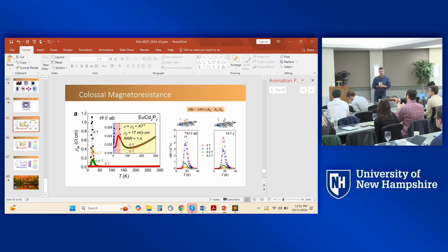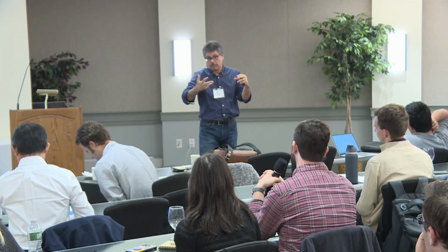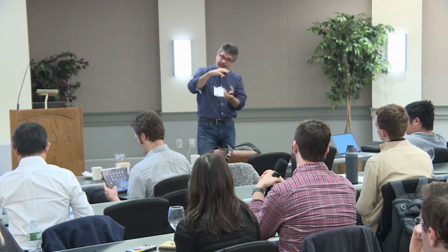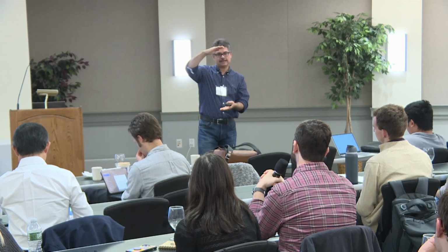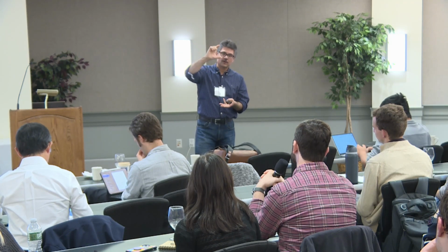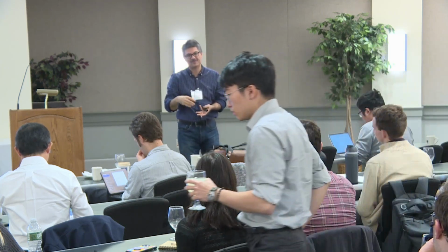So I guess opposite to what you see for this last set of materials, for the iridates, do you see them become more two-dimensional when you add the silver? Oh, that's a good question. In those systems, when we go from, for example, lithium to silver, it actually becomes more metallic. However, I can explain that in the sense that silver makes a lot more covalent bonds with oxygens, and it's a larger atom, so it increases interlayer separation, and one can say the system can become more 2D in that sense. But if you look at the electronic structure, you'll see there is some finite covalent bonding between silver and oxygen, and that actually prevents you from going to 2D. That's a good chemistry question, actually. Thank you.